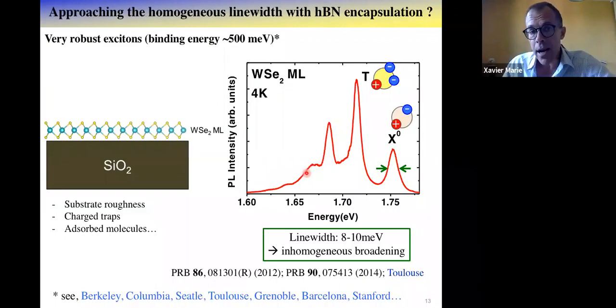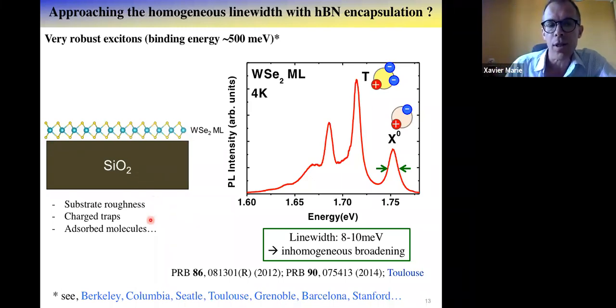So it is clear that initially, as everybody 8-9 years ago, what we did is that we investigated very basic samples, as sketched here: exfoliated monolayers, just transferred on a silicon oxide, silicon substrate. It turns out that this kind of substrate, silicon oxide, is not particularly flat. You have a roughness. You may have charge traps in your substrate. And on top of that, the surface is not protected. So you have adsorbed molecules and interaction between the charges around and your exciton in your monolayer.